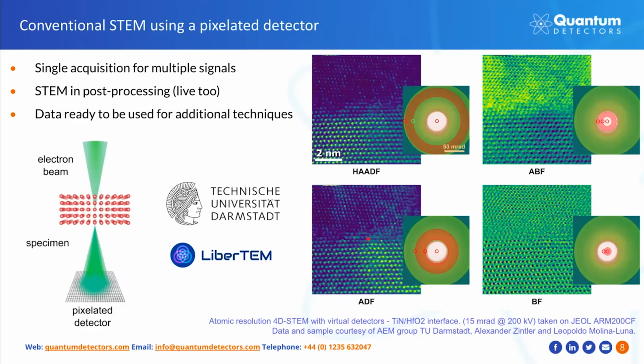MerlinEM users at Technical University in Darmstadt collected convergent beam datasets of a titanium nitride and hafnium oxide interface with a 15 milliradian probe convergence semi-angle. We have then used the user-friendly LiberTEM software, which supports MerlinEM datasets, to plot standard STEM signals in post-processing. You can see that for example, the high angle annular dark field signals show the brighter part of the sample in the bottom, brighter atomic columns, which correspond to hafnium, which is the heaviest atomic element in this sample.